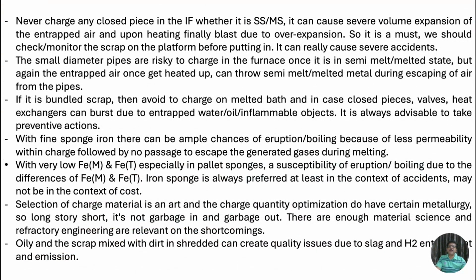Never charge any closed piece in the induction furnace, whether it is SS or MS. It can cause severe volume expansion of the entrapped air, and upon heating finally blast due to overexpansion. So it's a must: we should check and monitor the scrap on the platform before putting it in. It can really cause severe accidents.